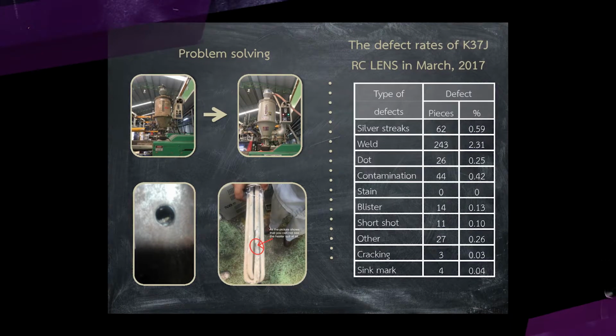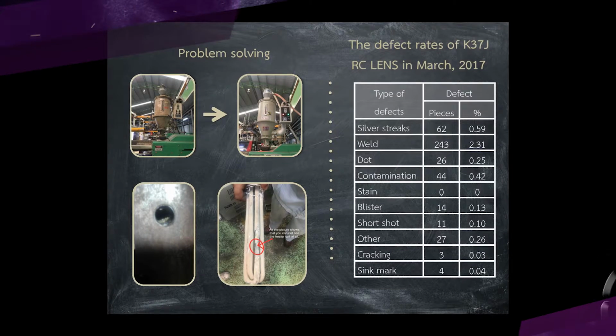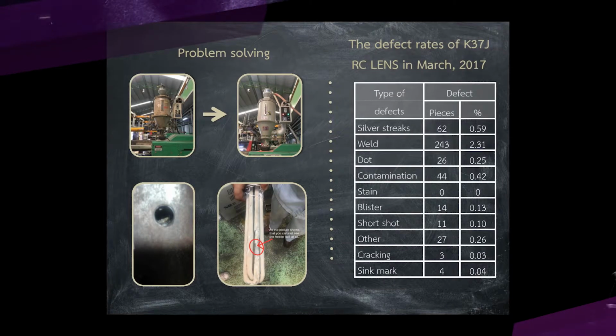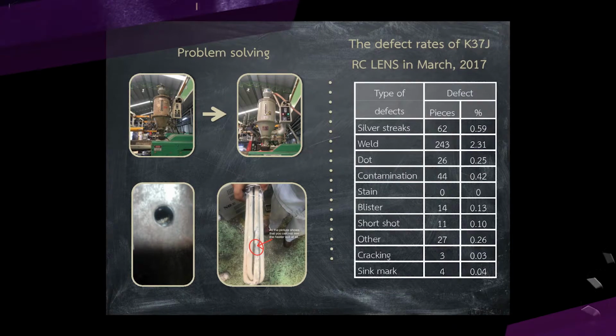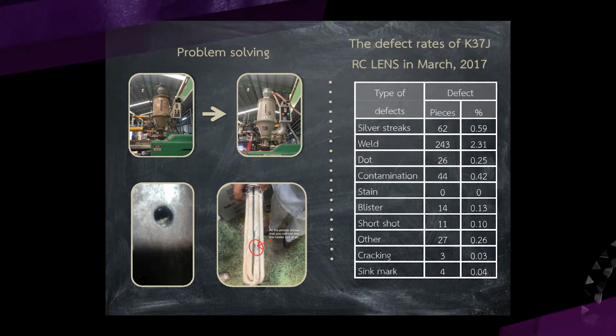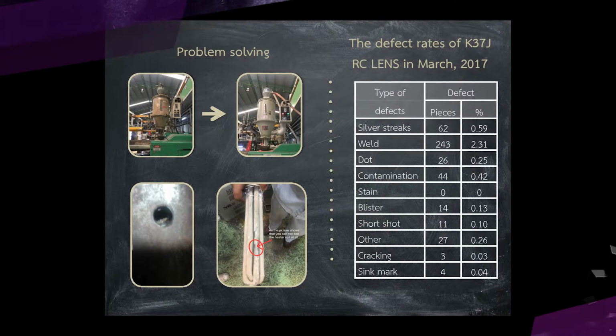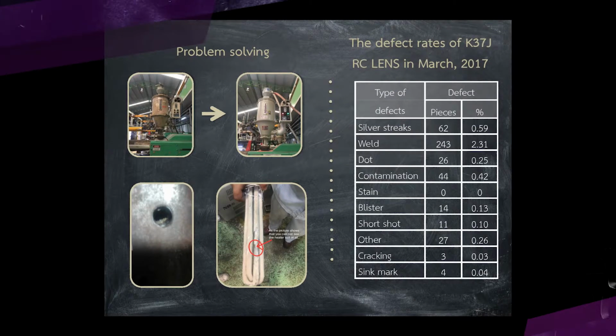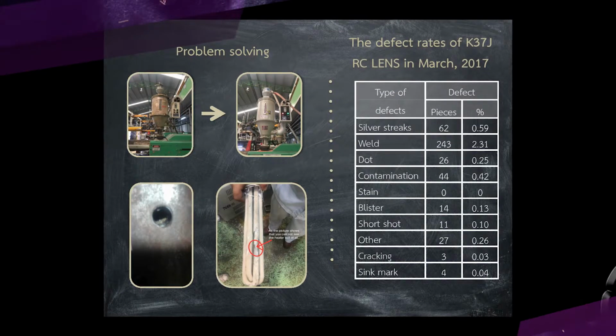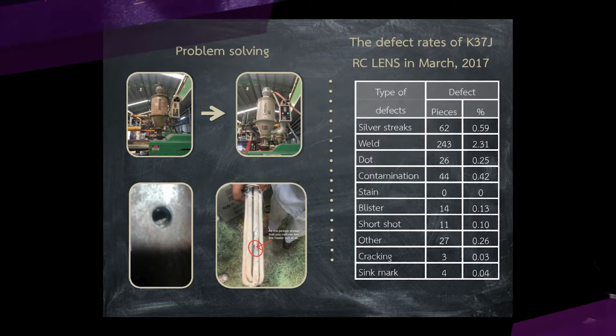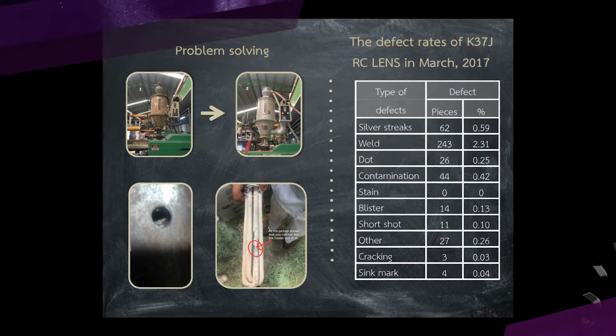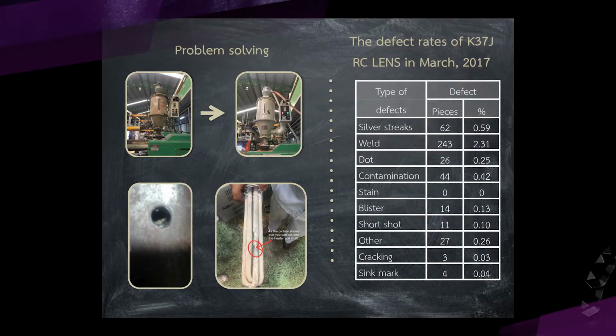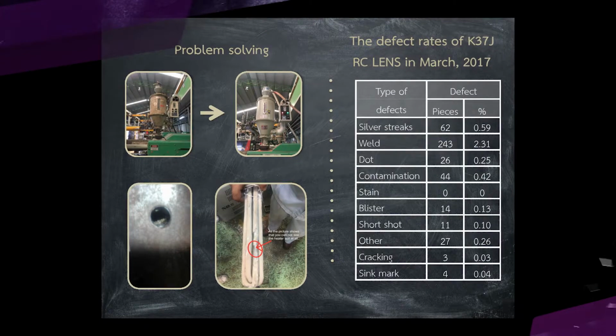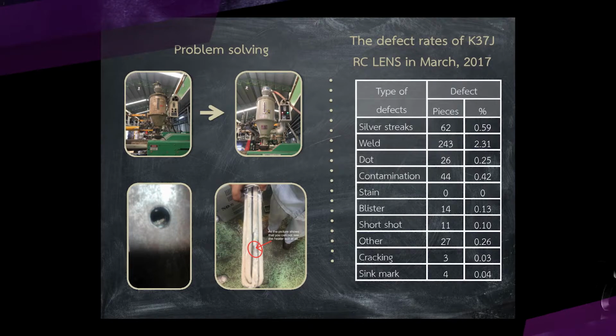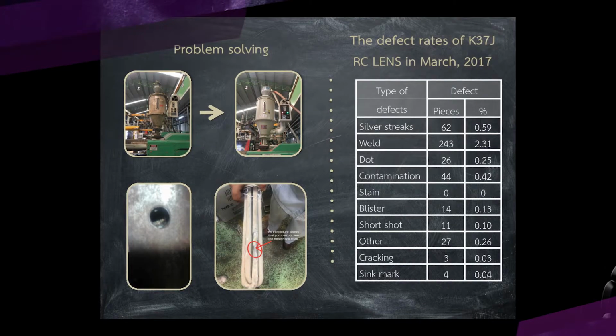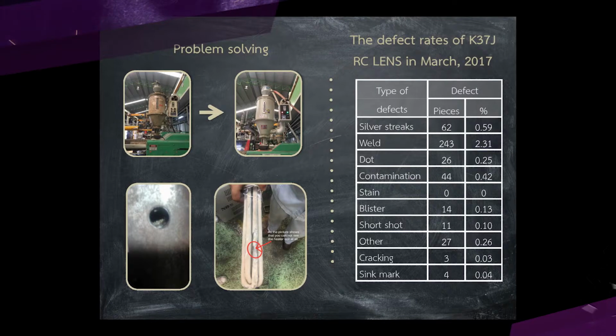And for weld, it was found that the cause of weld is from water. Water that was used inside the factory is a mixture of groundwater and tap water which contain dirt, and it blocks the hole, which affects the mold temperature, causing weld. So the solution to this is to renovate the water system, but it could not be done recently because our production line has to completely stop in order to change.